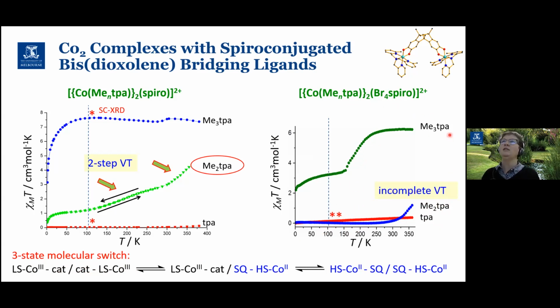And really quite interesting is the trimethyl TPA case. Now both the magnetic susceptibility and the crystallography at 100 Kelvin are consistent with us at that temperature being in the mixed valent state. Okay, and then again, we did variable temperature crystallography as we heated that up, and our magnetic susceptibility measurements are consistent with just seeing that second step, if you like, of the VT transition. So that's what we call a partial VT transition.